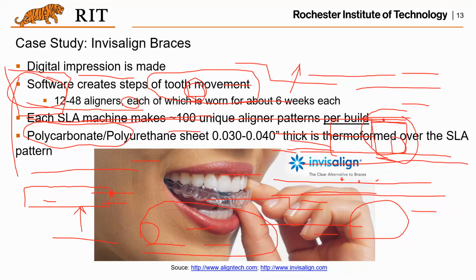All these aligners need to be fabricated first by 3D printing to print a model of the teeth, and then thermoforming to generate this aligner based on the printed teeth, right? And the material is polycarbonate or polyurethanes. Basically you want to have very thin layers for this material, and at the same time its strength should be good enough for the purpose to align the teeth.